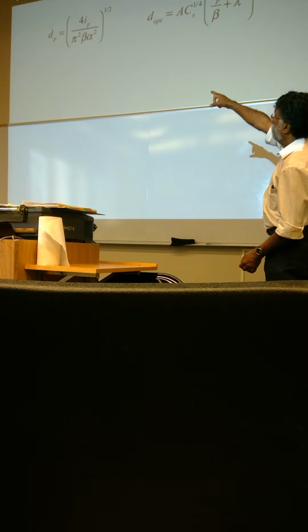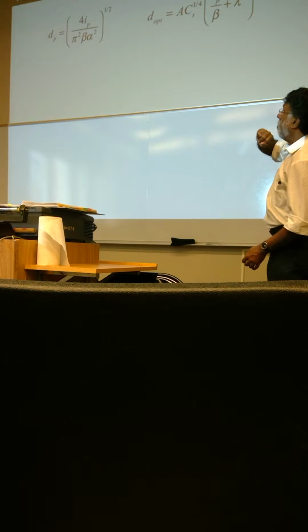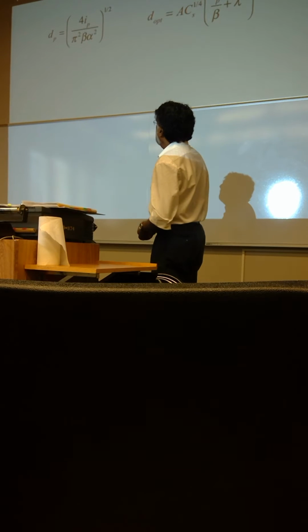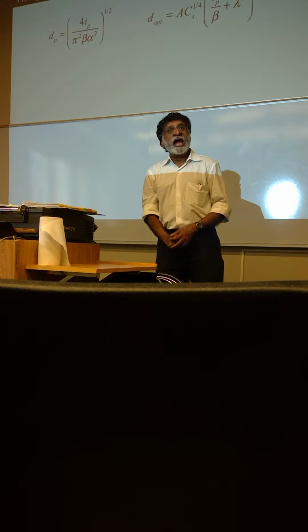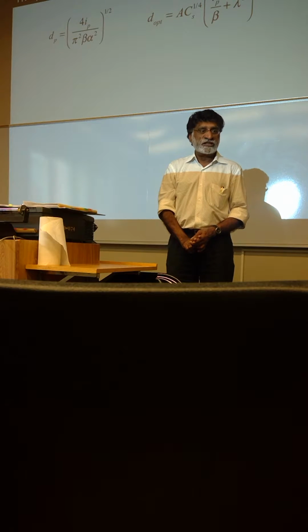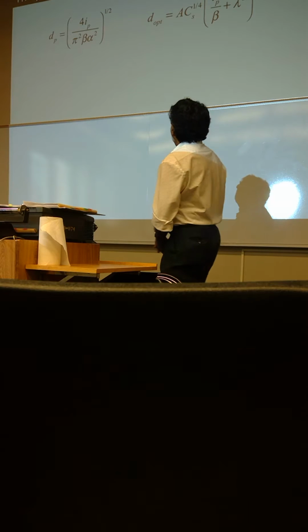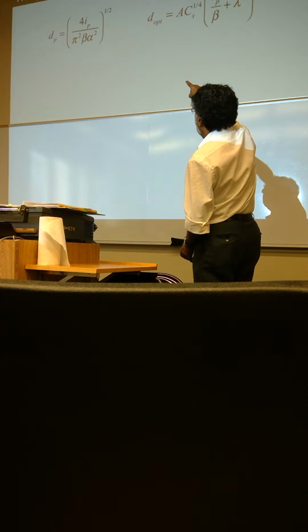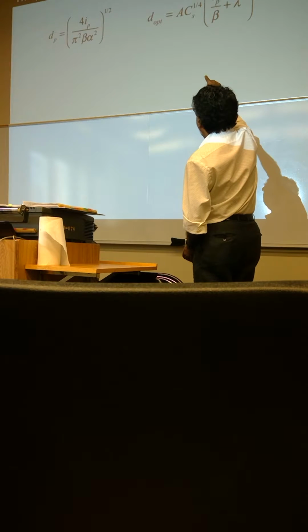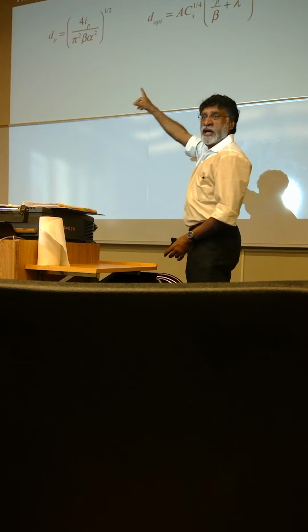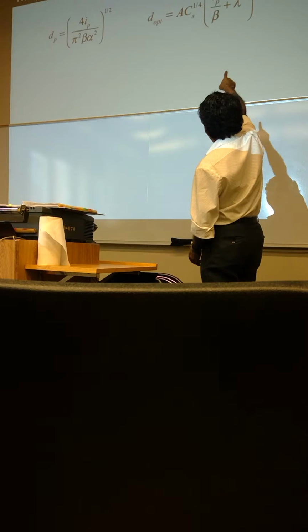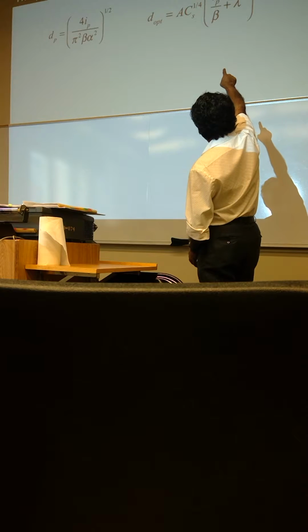One is the diameter of the probe. It depends on the current. It depends on the brightness beta. And it depends on the angle alpha, which is the angle of convergence. But as you can see, the optimal size of the probe depends also on the aberration of the lens. That is, on the right side it is CS, and it also depends on the wavelength.